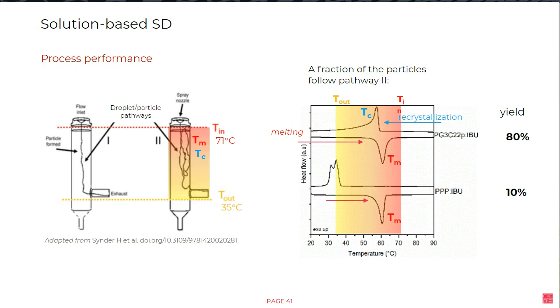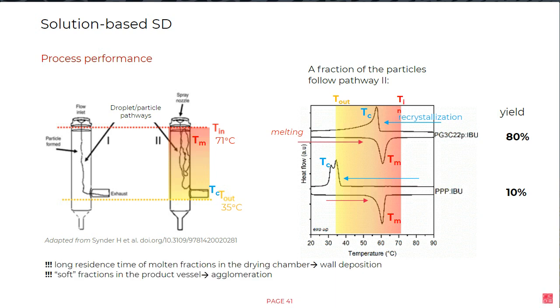In the case of tripalmitin, the recrystallization is very far away from the melting, as you can see. So the existence of molten fractions in the drying is unfortunately longer. Also, a fraction of these particles will stay partially molten in the outlet, which will also increase the agglomeration of the system. So basically, a long residence time of molten fractions in the drying chamber will cause wall deposition in lipids, and these soft fractions in the product vessel will cause agglomeration and, of course, impact the yield.